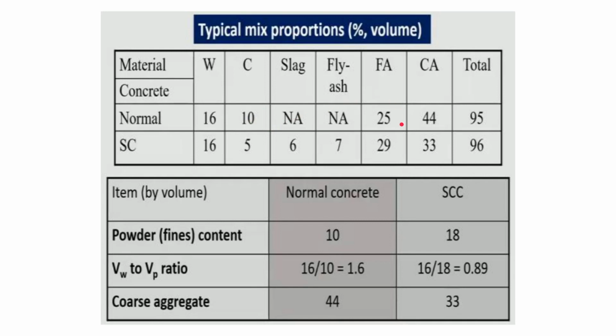And if we take sand, sand is again 4% more. So 8 plus 4 is 12, and 14% more, 12 and 14%. 14% by weight and 12% by volume. And here if we say the coarse aggregate, it is 11% less. So the total is 95 and 96%, and the rest are probably the voids.